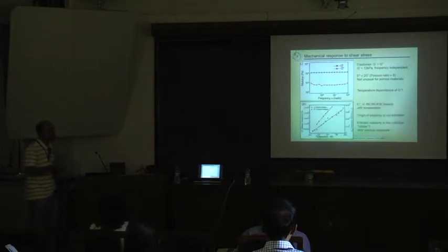What we then started looking at was the temperature dependence of this modulus, and that was something which we found very unusual. So here's the shear modulus and the Young's modulus, the elastic modulus, as a function of temperature spanning from minus 20 Celsius to plus 120 Celsius, so a 140 Celsius range in temperature. And what you see is essentially a linear increase. So E prime is always about 2 times G prime, so the Poisson ratio stays 0. But you see something that looks like a linear increase over 140 Celsius in temperature.